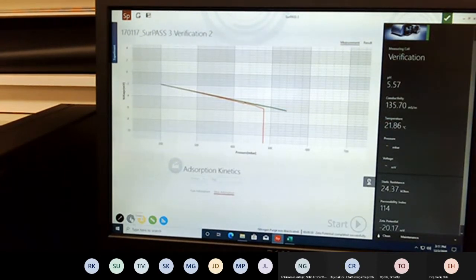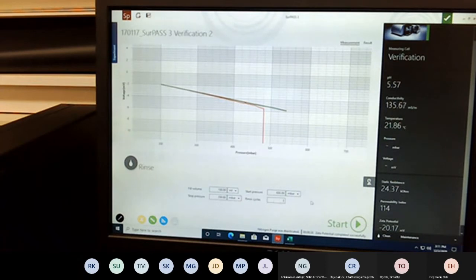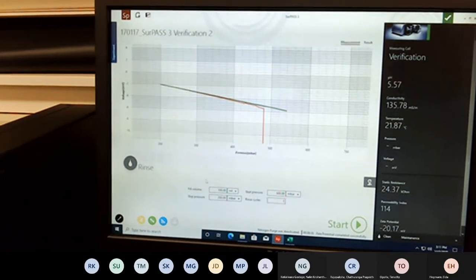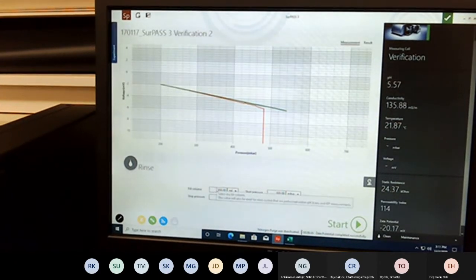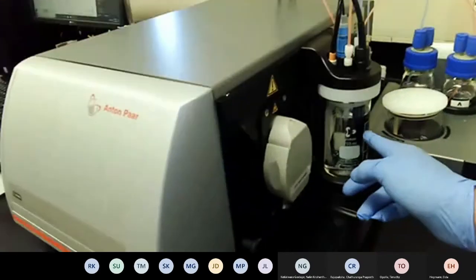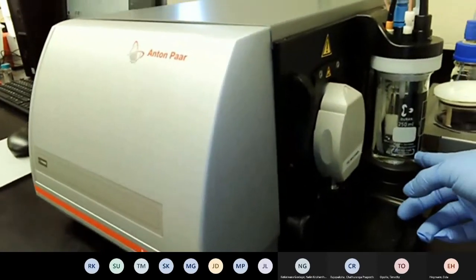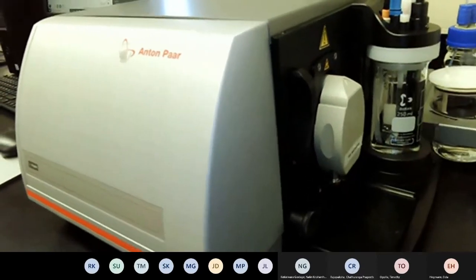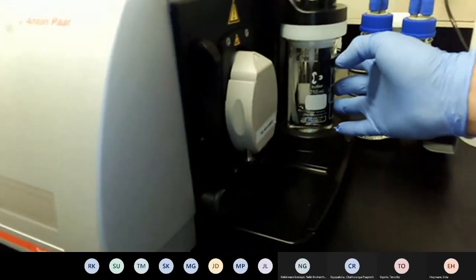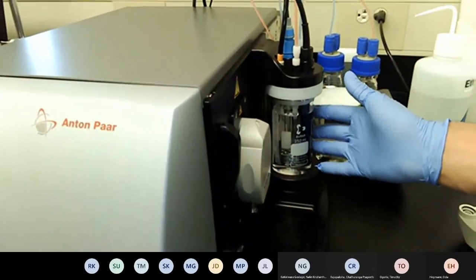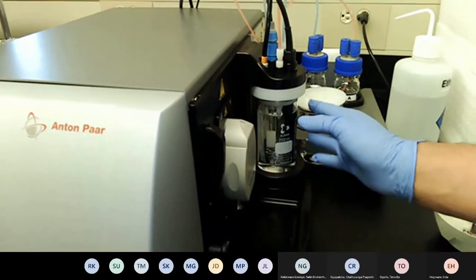To start a measurement, we're first going to rinse, and in this case, we'll rinse it about 5 times. Well, actually, just for the sake of time, we'll do it 3 times. Again, all of these parameters that you see here are pretty much what you're going to be using for every sample. You're going to fill with about 100 milliliters of electrolyte solution. The beaker is only about 250 mils, so if you ask for more, you're going to have to use a bigger beaker or you just won't have enough electrolyte to fill the measuring cell. But like I said, 100 mils is usually enough. You have 200 in here roughly, so it should be good for most of your measurements.